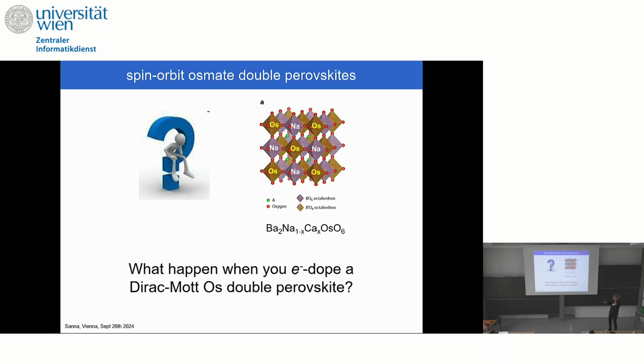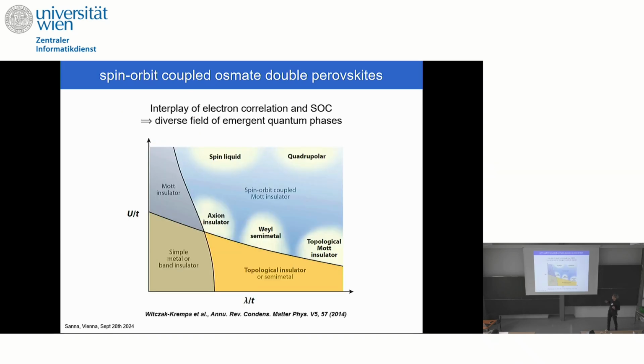And in particular, we were wondering what happened when we electron dope the Dirac-Mott osmium double perovskite that we have already discussed a lot during these days and today mainly, but also the first day. We have already seen this plot a lot of times, but it is important to stress the fact that with these double perovskites, we are typically in a condition where both λ and U, so both the spin-orbit coupling and the electron-electron correlation, are strong.